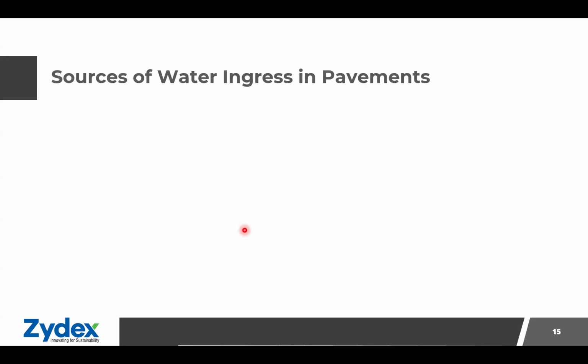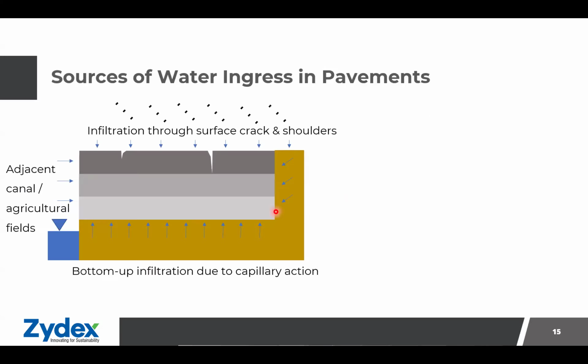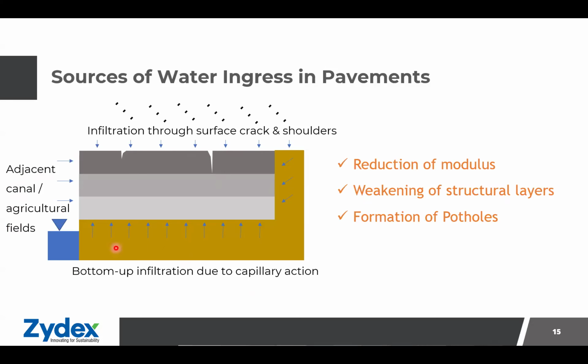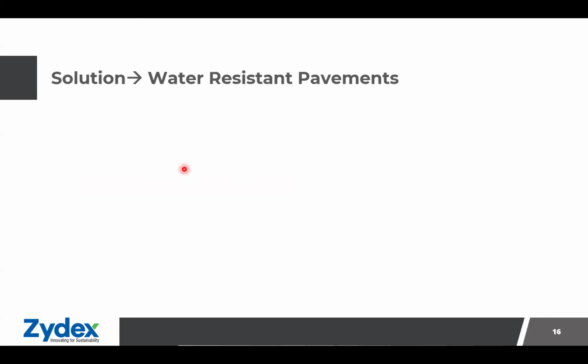Now, talking about the impact of water, we have multiple sources of infiltration in pavement. That includes the surface infiltration through the cracks and shoulders. We have bottom infiltration through the capillary action also, and there could be side infiltration due to agriculture fields or an adjacent canal. So this water leads to the degradation of modulus of the structural layer, that eventually leads to the weakening of the pavement layers and their bearing capacity, and eventually leads to the formation of potholes, leading to the failure of the pavement.